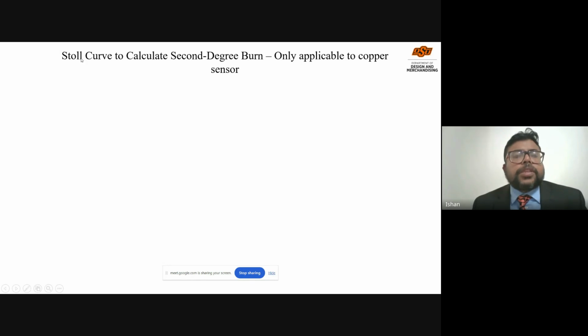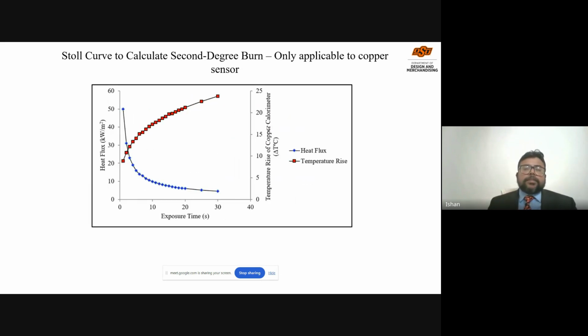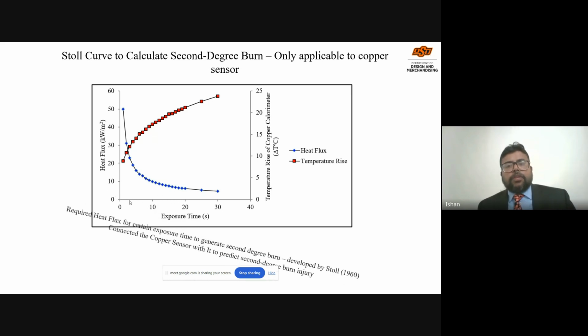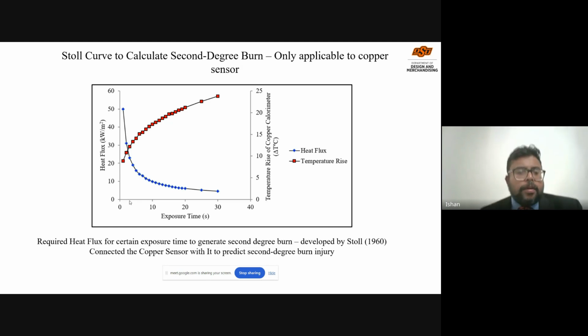There is another one, software based on the Stoll curve. That is only applicable to the copper sensor. We cannot use the Stoll curve in multiple other areas. Stoll is the name of the researcher. When she did the research, she gave the exposure for different amounts of time, and for a particular heat flux, she tried to calculate when the second degree burn occurs. And when we use the copper sensor, we see how the temperature rise is occurring. So when our temperature rise curve matches with the copper sensor or the Stoll curve at this particular point, we call it the time for second degree burn. So for example, if we go down from this point, we can calculate the second degree burn for any clothing when we put it there. When I show you the test, that will be more visible.